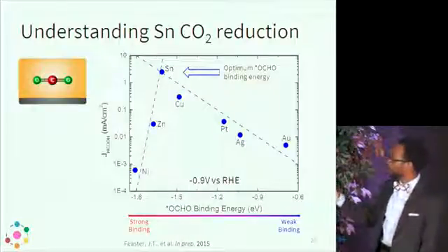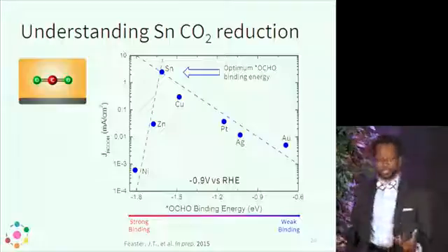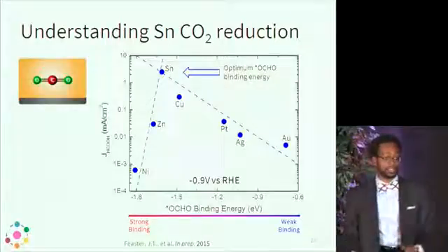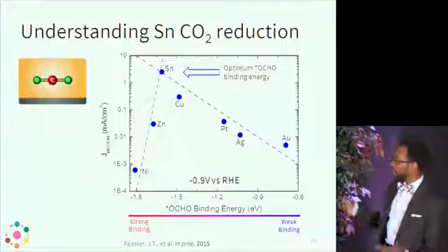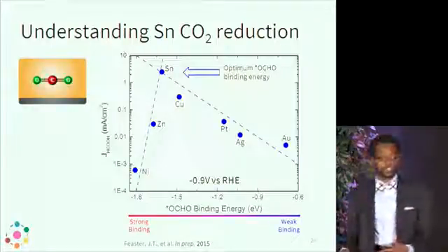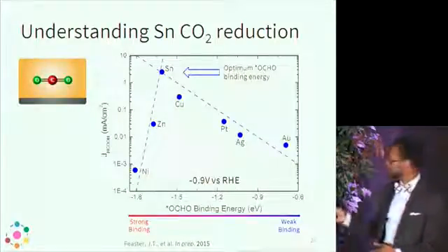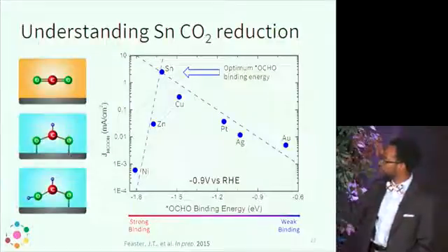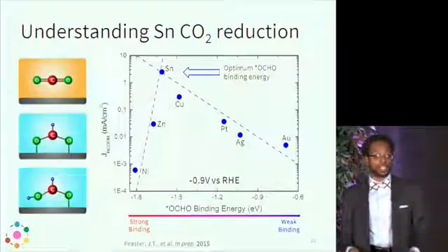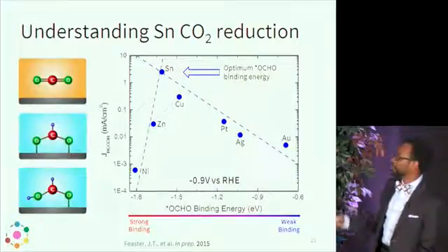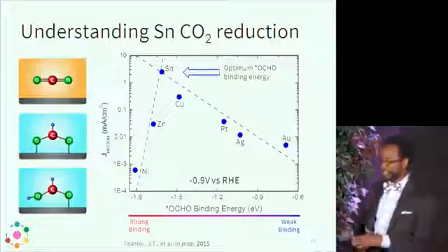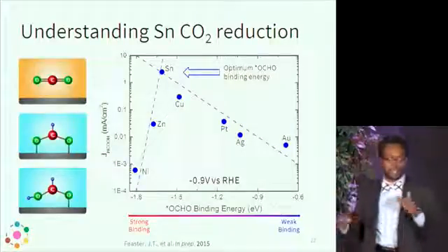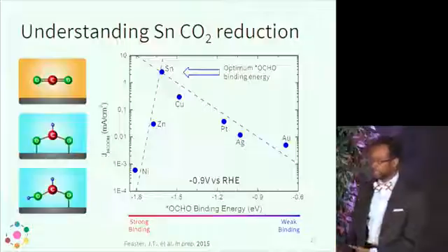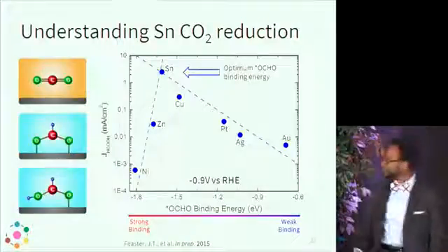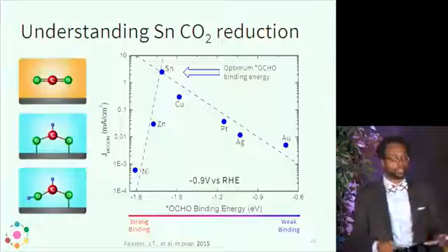So with the y-axis still being our experimental data that we were able to show for all these different metals that we tested in this setup at negative 0.9 volts versus RHE, and then our x-axis being theoretical DFT calculations of the OCHO binding energies, which corresponds to an intermediate that looks something like that to the left, you actually are able to completely recapture the volcano trend. And what's the greatest part about this particular figure is that tin is at the very top of this volcano. And so it has this optimal binding energy for this key intermediate that then results in it being able to make formic acid.